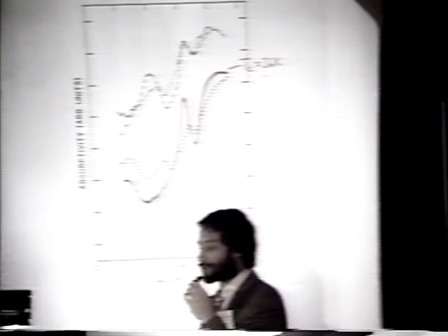Now, if you look at several other compositions, all of which do not show high TC, basically different strontium concentration, also somewhat different copper in one sample, you see that this strong phonon feature is much weaker. There seem to be several phonon peaks, and the height of the infrared electronic absorption is diminished. Actually, because the Drude background is coming up here at the same time for the others, because they're poor conductors, it's diminished even more than it would look at a quick glance if you look at the deviation from Drude.